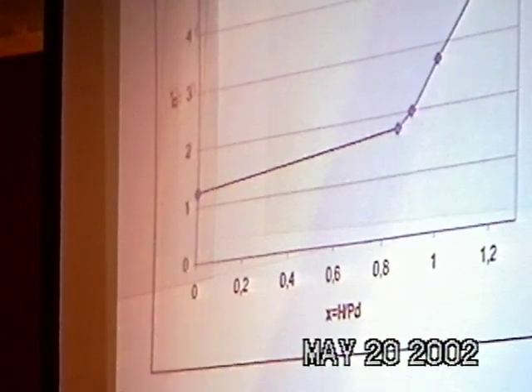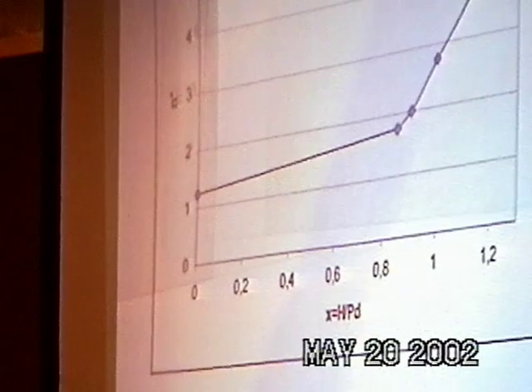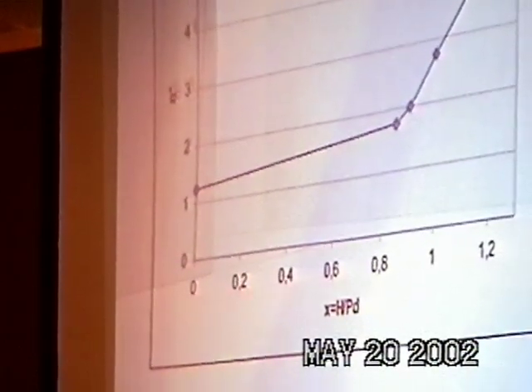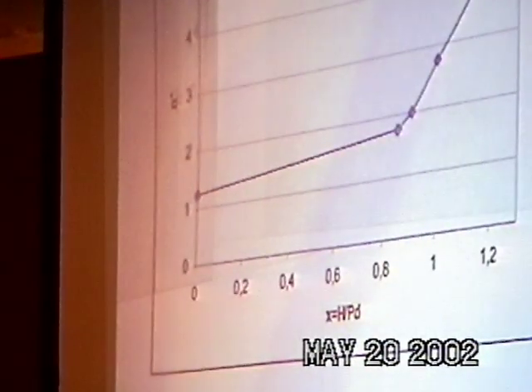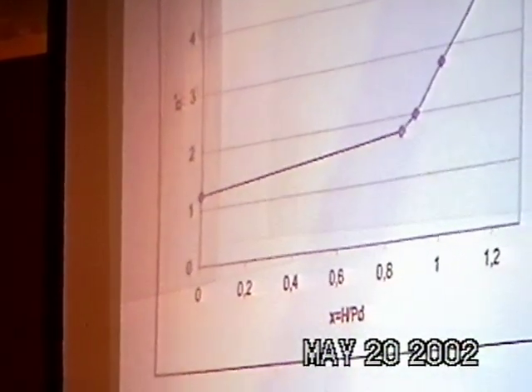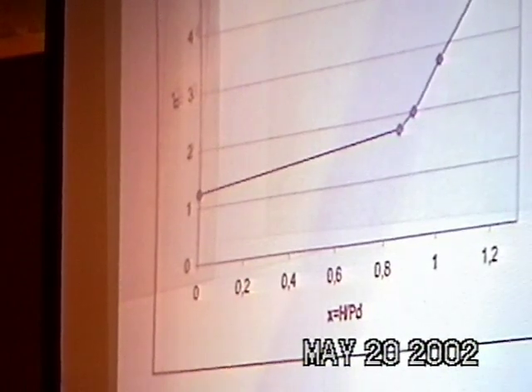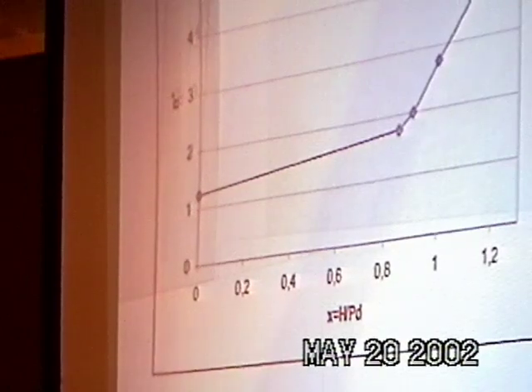But if we discuss what that means, we get an astonishing result. Namely, let's consider the first part of the graph. In this first part, which corresponds to the beta phase, each new hydrogen entering into the lattice contributes 0.7 electrons, more or less, to the conduction band. The other 0.3 are given to the low-lying deep band and contribute to a change in the magnetic susceptibility, which is actually observed. So everything is regular, everything is accounted for.